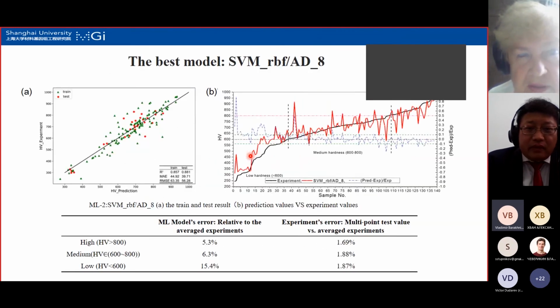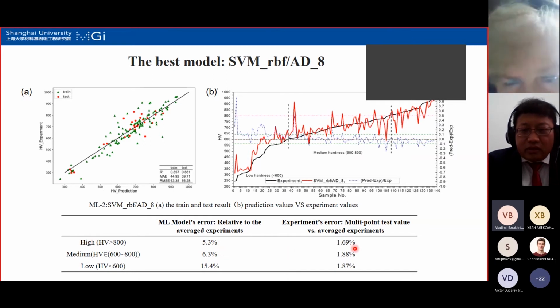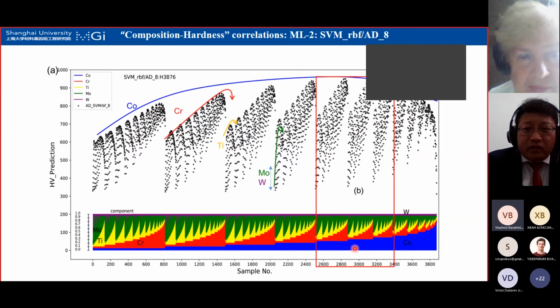We do several rounds, improving our accuracy, and the best model is the support vector machine. We can reach an error of around 5 to 6%, and the intrinsic experimental error is around 2%. So we are slightly higher than the experimental error, but it's pretty good. And after we have a good machine learning model, it can predict the hardness of alloys very efficiently. Basically, we can get the hardness of all possible combinations or compositions in this system.